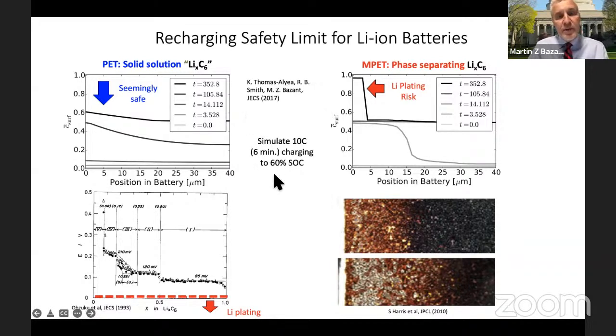So what we did in this paper, 2017, was on the left to simulate that experiment on the graphite particles at a certain high rate of charging. So let's say 6-minute charging, so-called 10C, up to 60% state of charge. And on the left, if you look as a function of position in the battery, the concentration at the surface of every particle is around 60%.